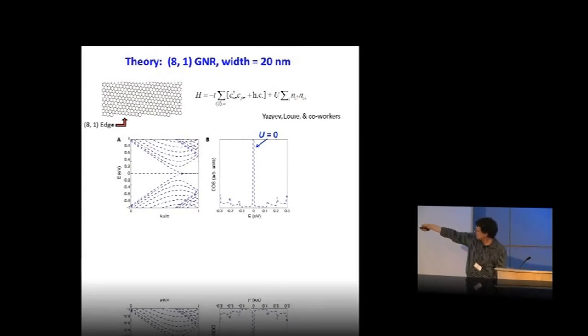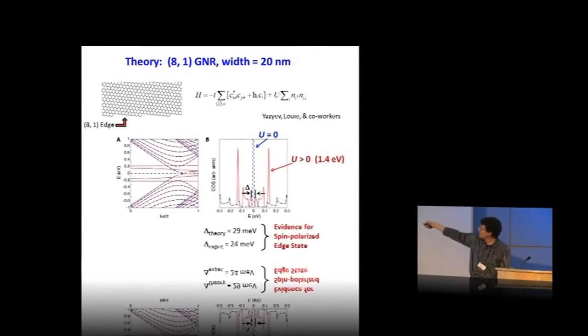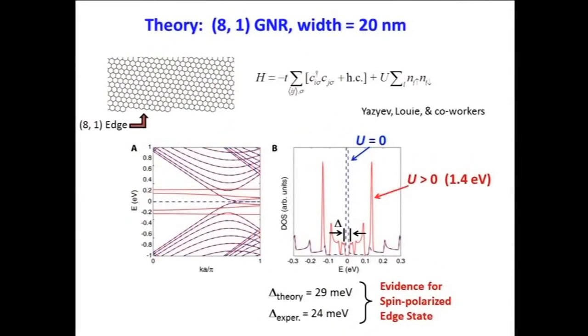And this is a calculation done in the absence of electron-electron interactions. What you see here is a metallic edge state at zero, which leads to a big peak in the density of states. Now, that's not what we saw. So in order to simulate what we saw, they had to turn on the electron-electron interactions. They did that using a mean field solution of a Hubbard model. And when they turned on the electron-electron interactions, that caused a gap to open up in that edge state. And that gap was of an order of magnitude very close to what we saw experimentally. So there's some agreement here between their theory and our data.